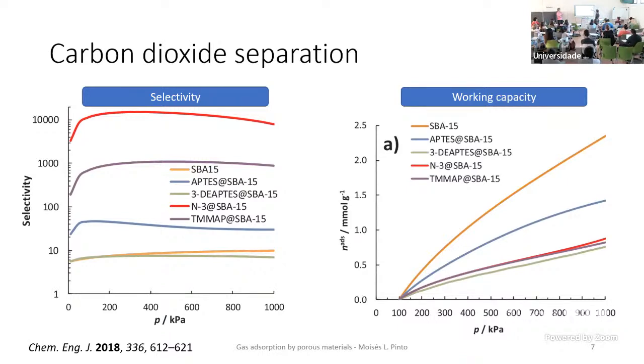Another aspect is, for instance, the working capacity. We can regenerate the material, but if we consider that we are going to regenerate only at atmospheric pressure, so if we increase pressure and then go back again and decrease to atmospheric pressure, we have always some amount that stays inside the solid. Yes? And this decreases the working capacity. So if you see in here, the amounts are less than in the initial isotherms that I highlighted over there. So there are some aspects that afterwards can be analyzed to see if the materials are interesting or not for application.